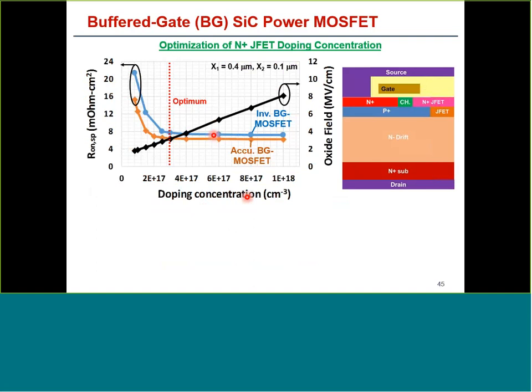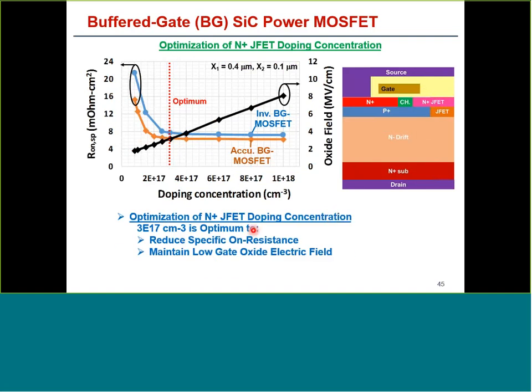So you can see here in this chart that as the JFET doping concentration is increased, we see a reduction in RDS(on) because this region is no longer pinched off and it settles down to good values. But if you keep increasing the doping, then the oxide electric field starts getting very high, and that is not good for reliability. So we believe that the optimum JFET doping concentration lies right here at 3E17, which gives us very good on resistance, and we still have low gate oxide electric field.